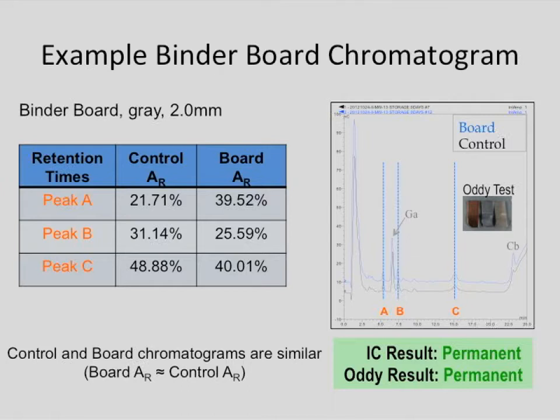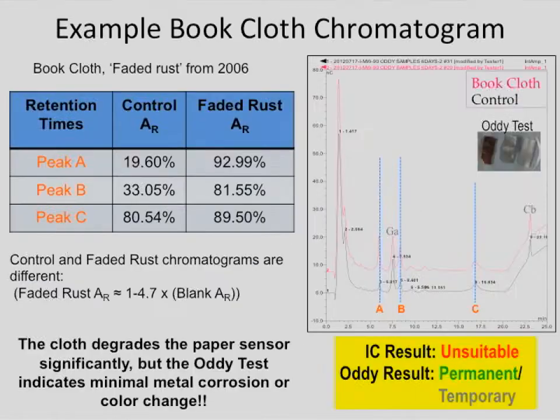Again, the Oddy test shows the same thing. You don't see any corrosion on these coupons. So this is a good match for the Oddy test.